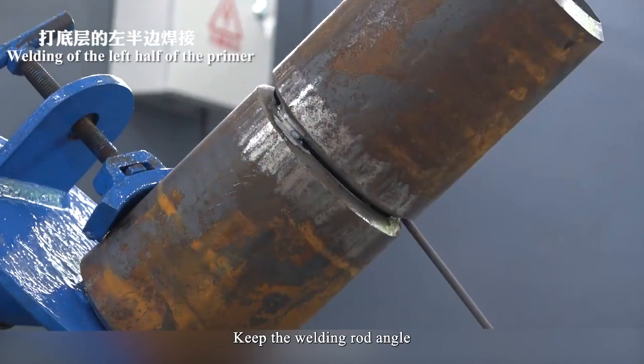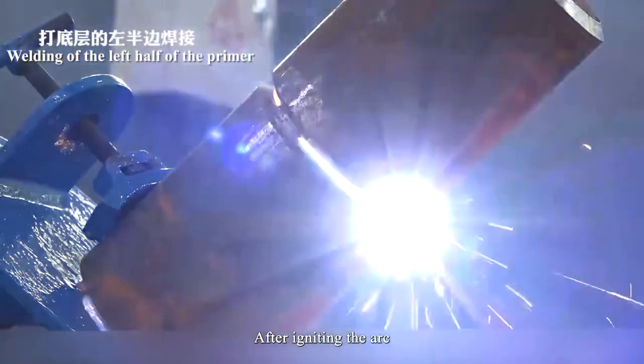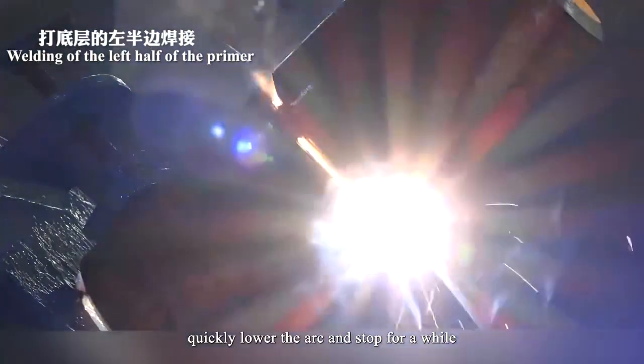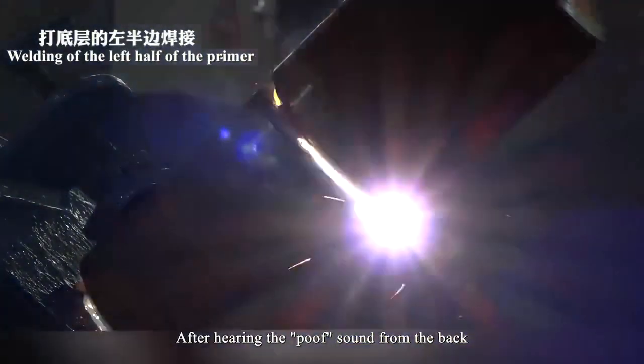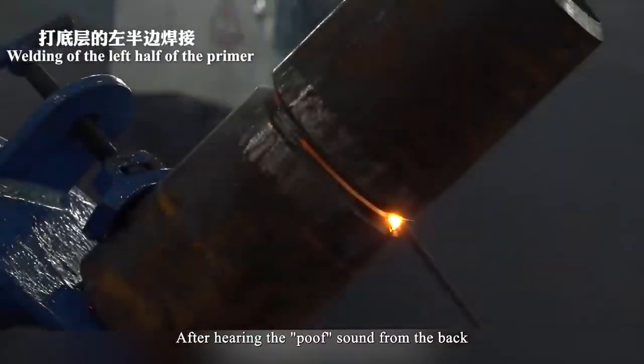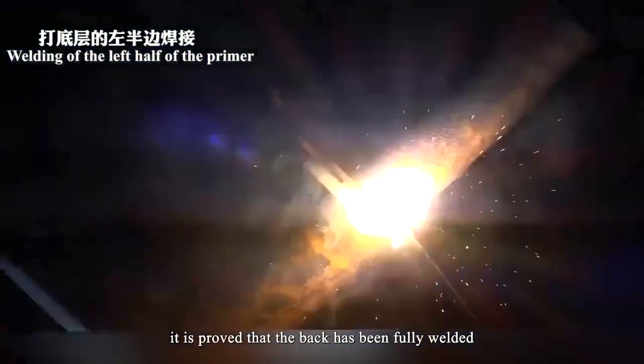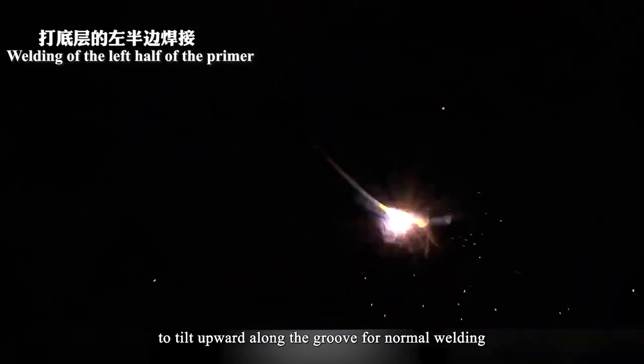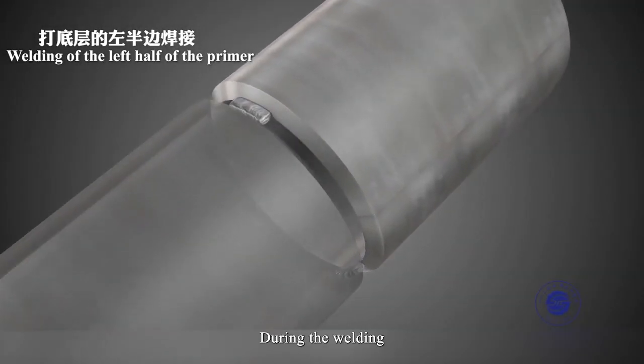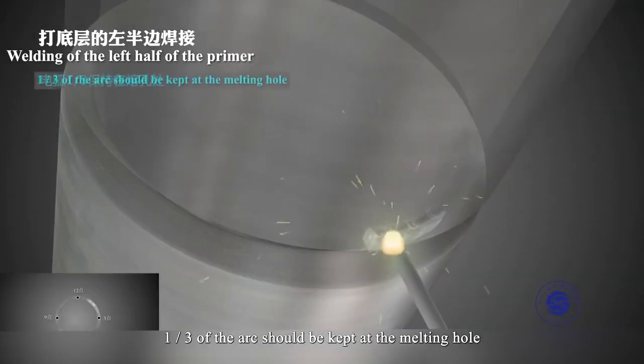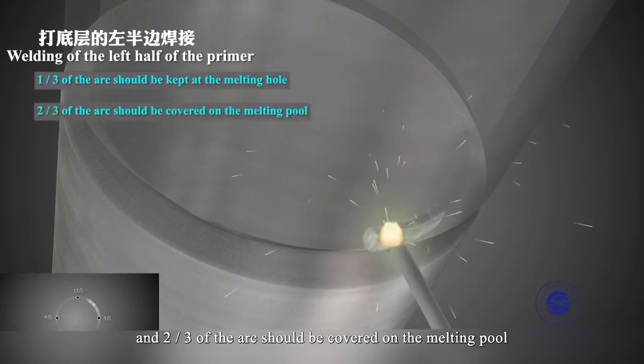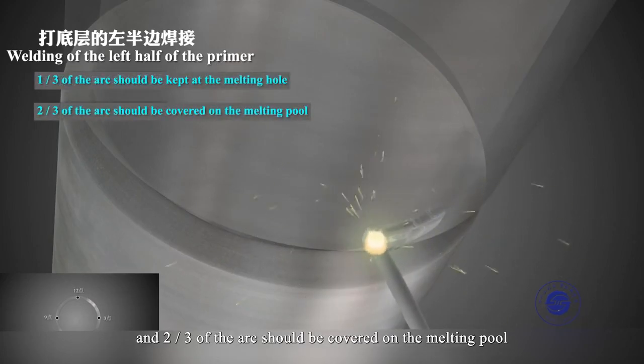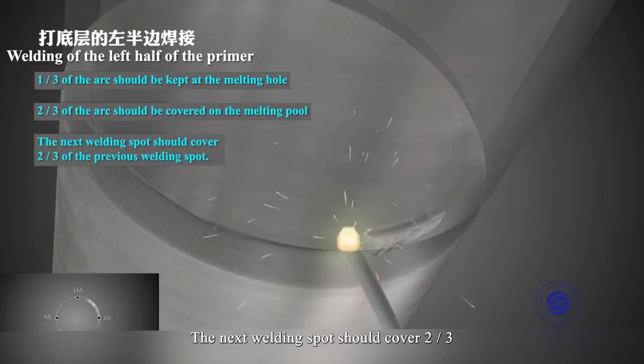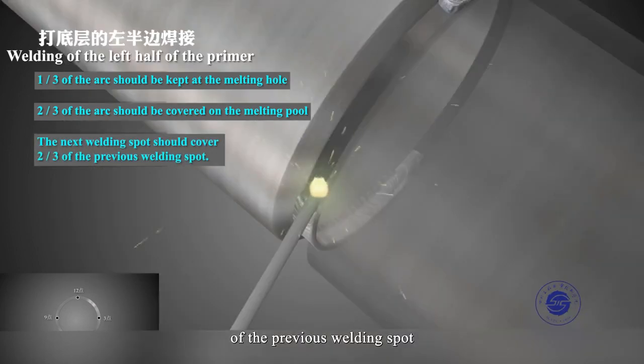Keep the welding rod angle. After igniting the arc, quickly press the arc down and stop for a while. After hearing the poof sound from the back, it proves the back has been fully welded. Use arc extinguishing to move upward along the groove for normal welding. During the welding, 1/3 of the arc should be kept at the melting hole. 2/3 of the arc should be covered on the molten pool. The next welding spot should cover 2/3 of the previous welding spot.